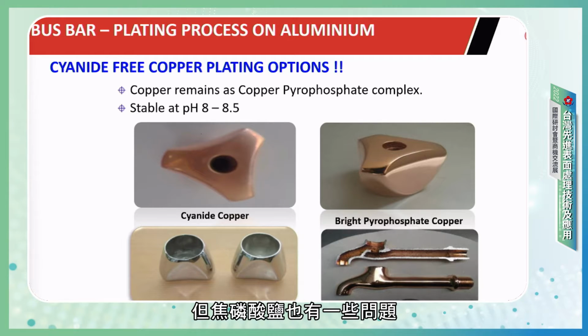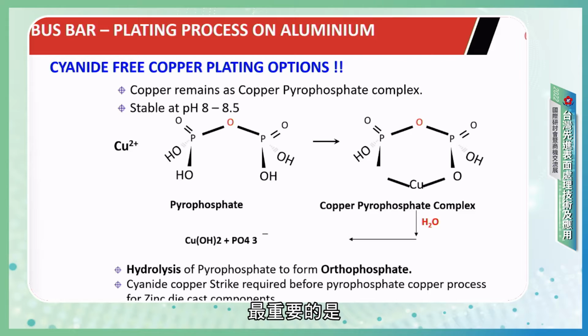But pyrophosphate is associated with some issues. For example, pyrophosphate is also not very user friendly with respect to waste treatment. And the most important thing is that the pyrophosphate ion has got some tendency towards hydrolysis, forming single uncomplexed copper. So if you have uncomplexed copper, there is a possibility that we might get immersion copper deposit, and as a result we will not have good adhesion. Now why does this hydrolysis take place? Because in the pyrophosphate complex, you can see there is an oxide linkage, and this oxide linkage makes the complex a little vulnerable towards hydrolysis.